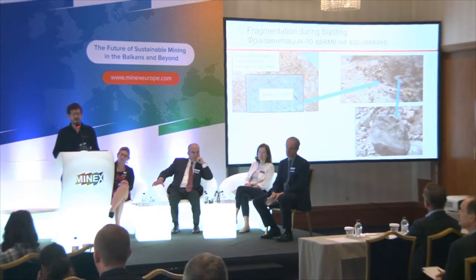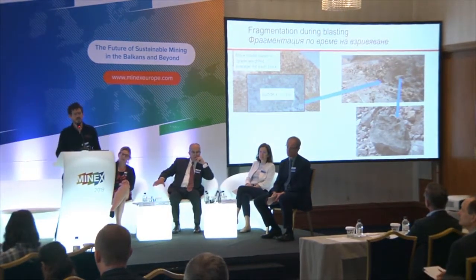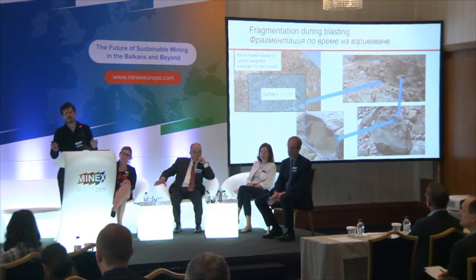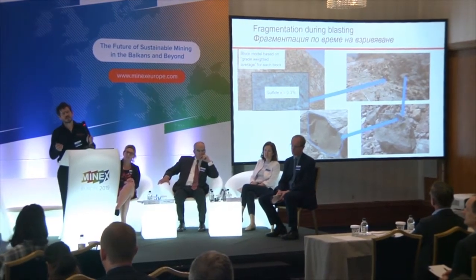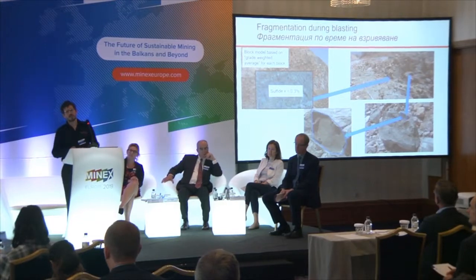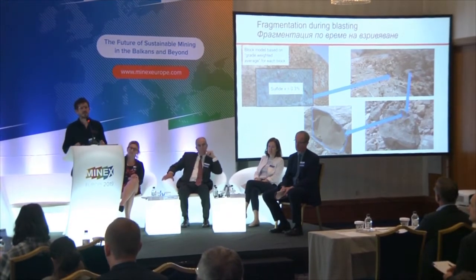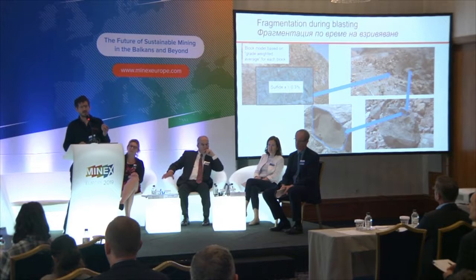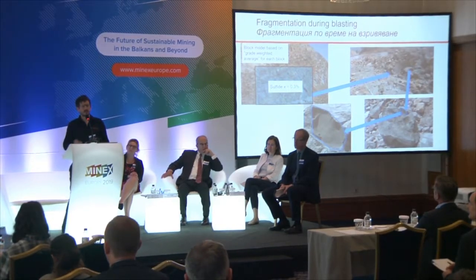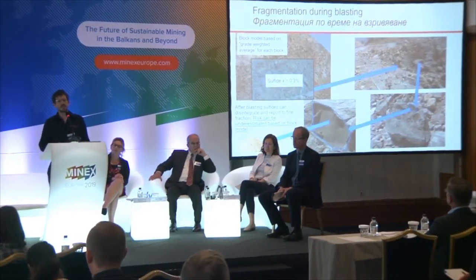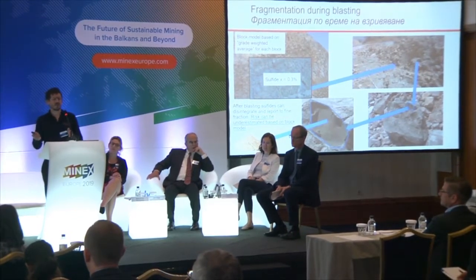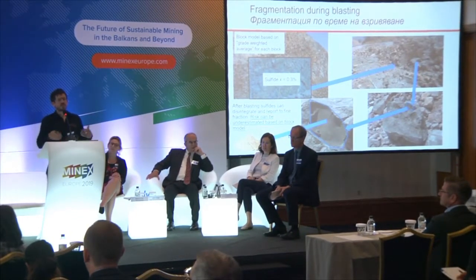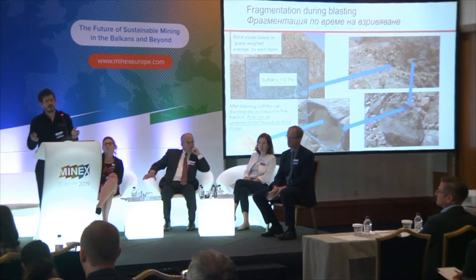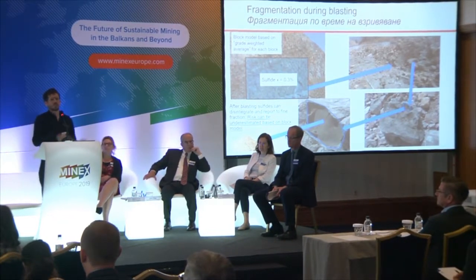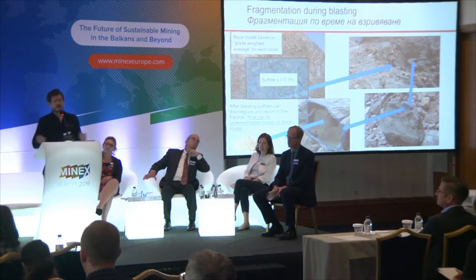after a blast, this is just showing the blast face. If we zoom in on a piece of material that's been blasted, you'll notice there's a big cavity. Now in that cavity were sulfides. The shock of blasting removes these sulfides out of the cavities. This is because the sulfides are generally weaker structurally than the host rock. So what that means is that after blasting, all those sulfides go into the fines. So although this is 0.3% low risk, actually what happens is that virtually all those sulfides report to the fine fraction, which is the high risk fraction.